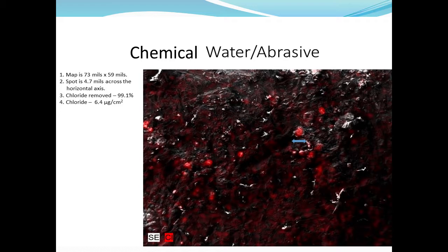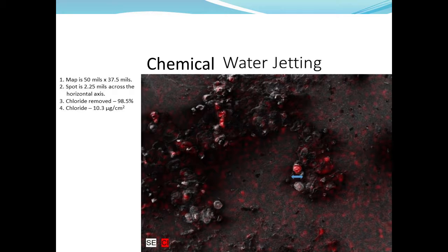salt deposits. And as you can see, this one is 4.7 mils across. So we've got 8 or 9 spots of salt in this area that we're looking at. I got a few of these because they look a little bit different, and there was one particular phenomenon that we noticed that we thought was interesting, not that we can explain everything. As you can see here, there are far fewer deposits of chlorides, but it's got 10.3 micrograms per square centimeter of chlorides. The area of the deposit here of this one is just a little over 2/1000ths of an inch in diameter.